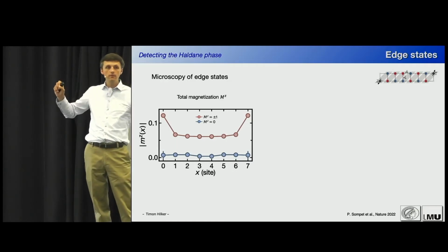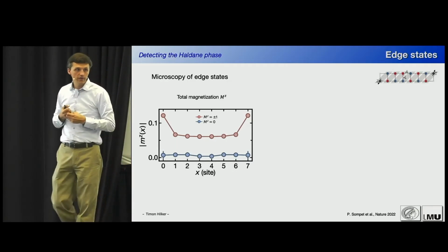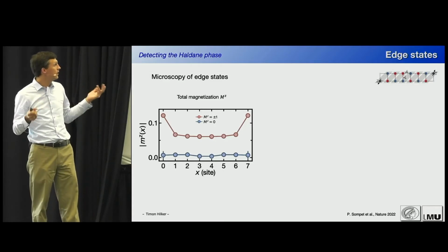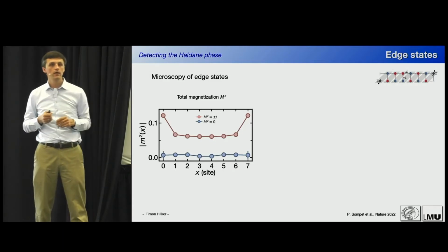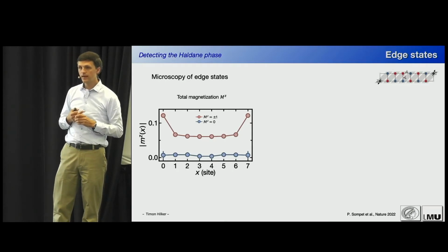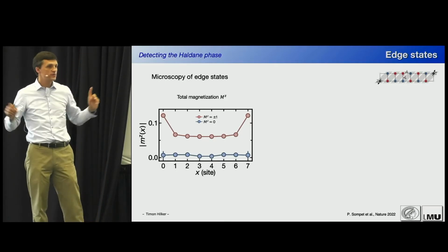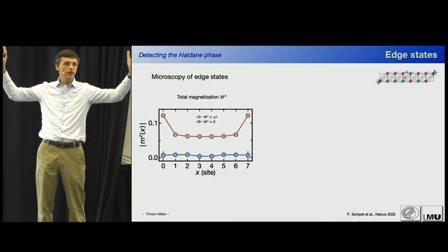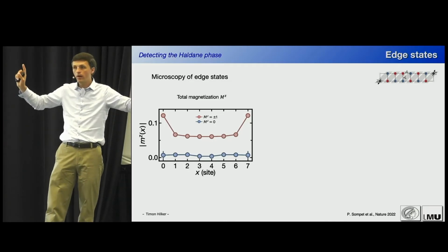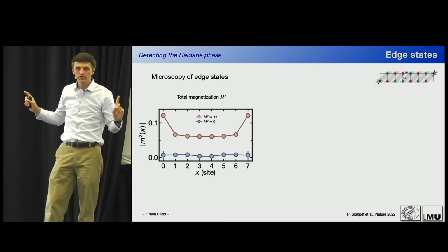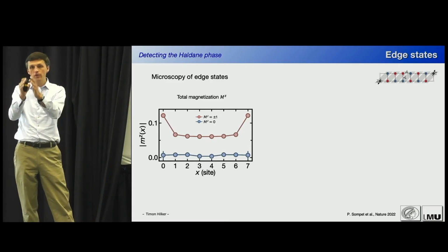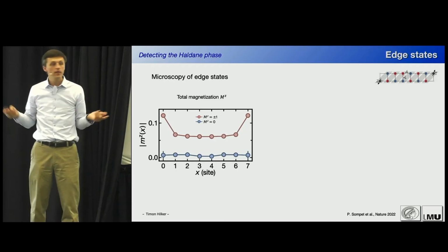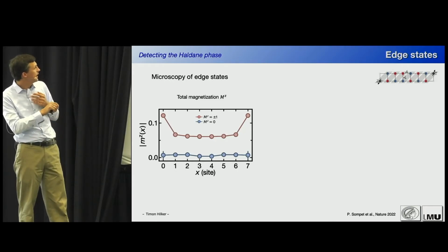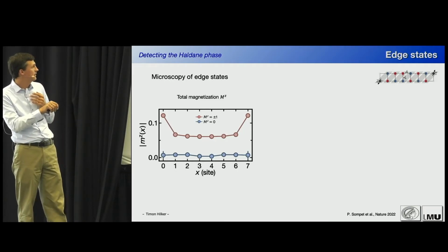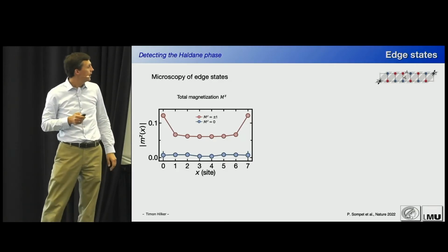So it's a spin-1 system, but the edge state should be of spin-1/2 nature. And we can see those in the experiment by putting one unit of magnetization into the system. Because these edge states are free to point in any direction, the lowest energy state will always be the one for one magnetization where this magnetization sits at the edges, because there it doesn't cost any energy. While if I put it into the bulk, I have to break a singlet bond, that costs some energy. So what we see here in red is how this magnetization dominantly sits at the edges. And then, well, this isn't quite 0 because we're not at 0 temperature.